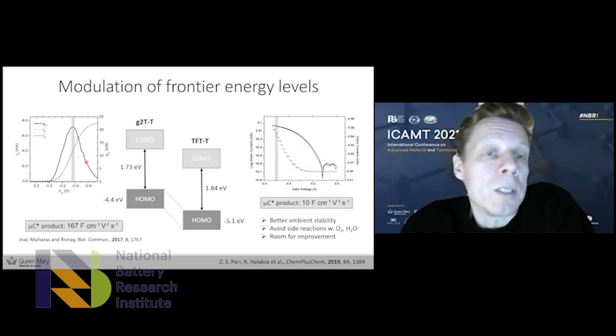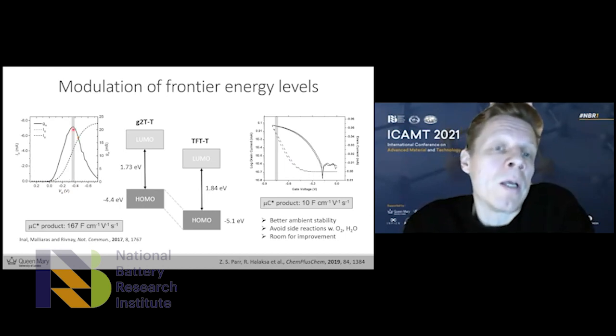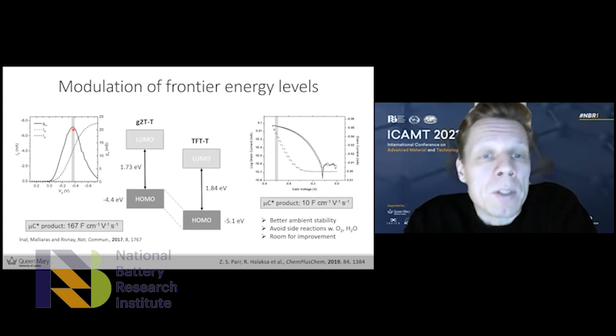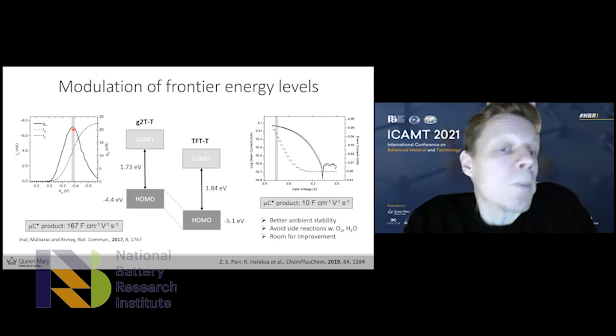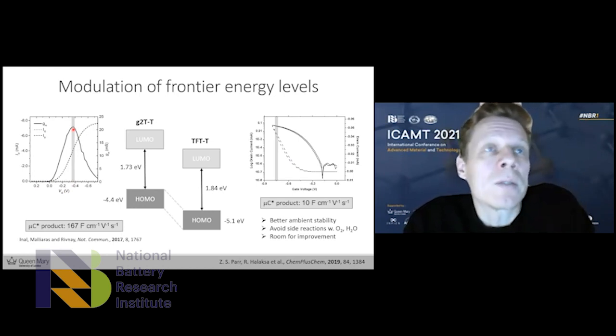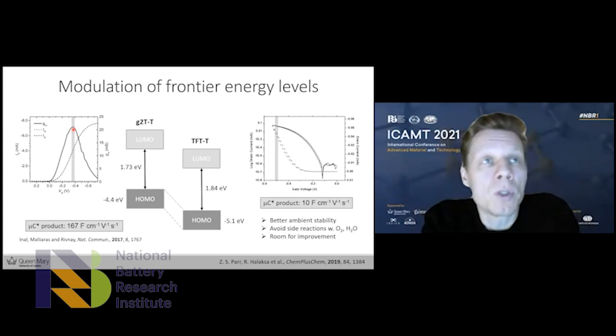On the left here, we see the transconductance in the solid line as a function of the gate voltage for the benchmark material. And we can see we get a peak transconductance at a relatively low gate bias around minus 0.4 volts, meaning that we can operate this OECT device, this biosensor, at low bias, where we don't need to worry too much about side reactions from the high bias.